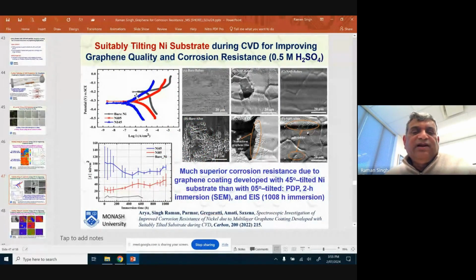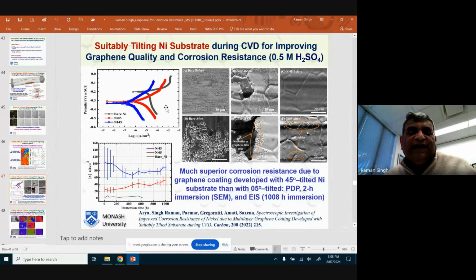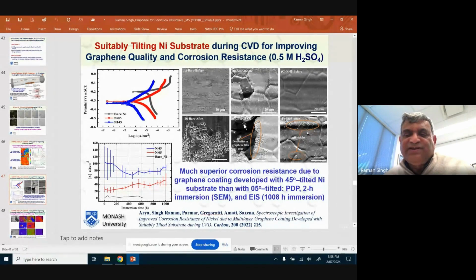When we did corrosion tests, you can see that the 45-degree tilted sample gave very good corrosion resistance. Post-corrosion macroscopy also showed that the 45-degree tilted sample still had good quality graphene intact, whereas the 5-degree tilted one had disruptions in the coating, as you can see. The 45-degree tilted sample gave very good corrosion resistance in sulfuric acid for a long time, over 1,000 hours or so.